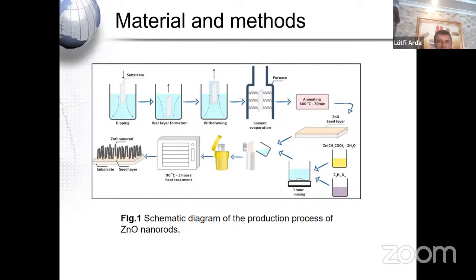We look at the figure. We dip the substrate inside the transparent solution. Okay, then we repeat this dipping and withdrawing process 5 times, and we coated a zinc oxide thin film on the glass substrate. But there is the solvent evaporation. We did it using a furnace, and the furnace temperature is 600 degrees Celsius for 30 minutes. After the annealing process, look at this part. Can you see my cursor here? This is the substrate. On the substrate there is the zinc oxide thin film.